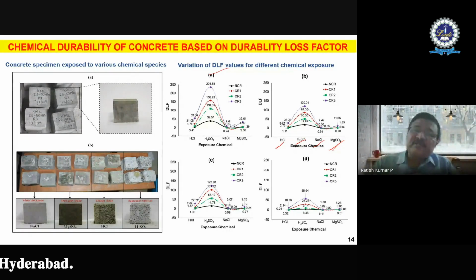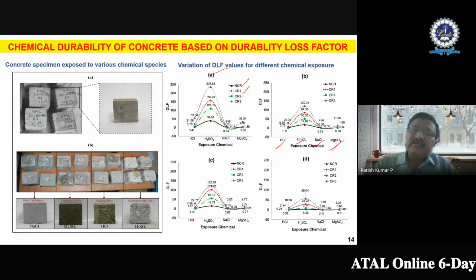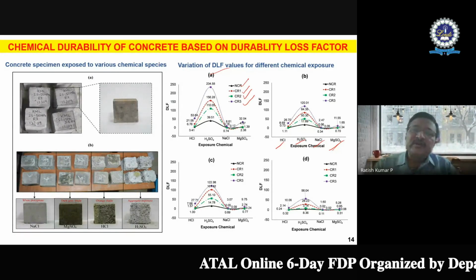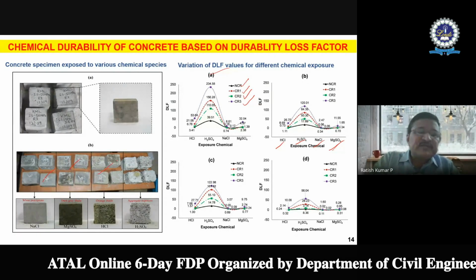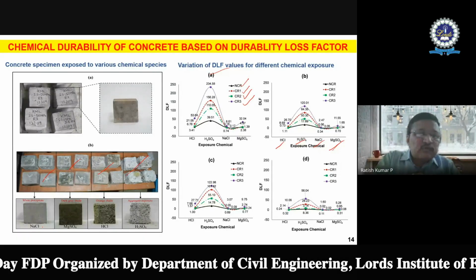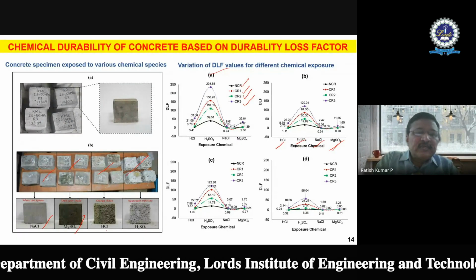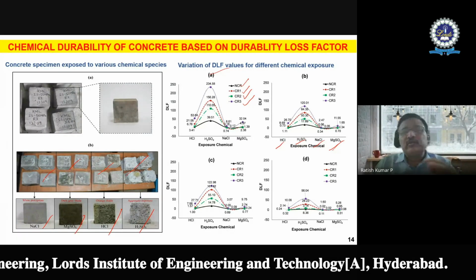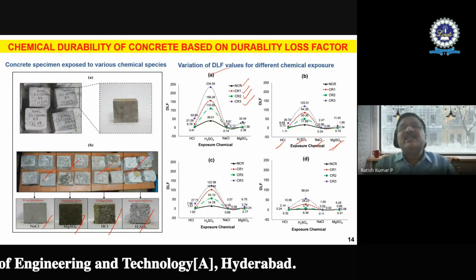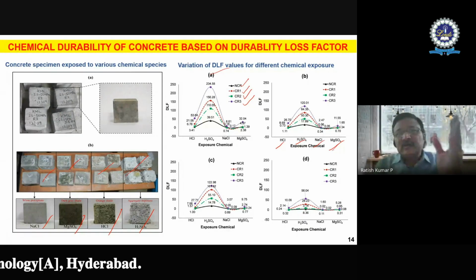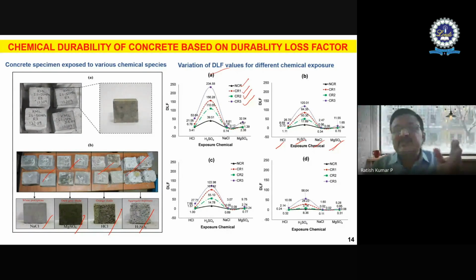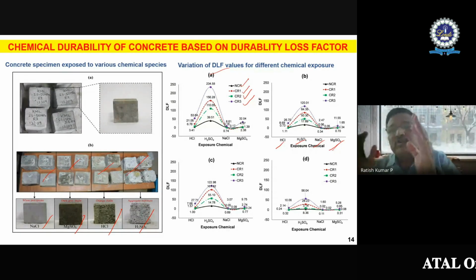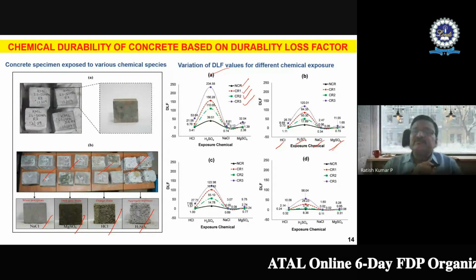I determine this with respect to conventional concrete, first generation concrete, second generation concrete, and third generation concrete. You can see these are the corresponding specimens I made, and they are exposed to NaCl, MgSO4, HCl, and H2SO4. I could get this parameter from a mechanical point of view, from loss of strength, loss of mass, and loss of dimensional stability, and come up with one unified factor called the durability loss factor.